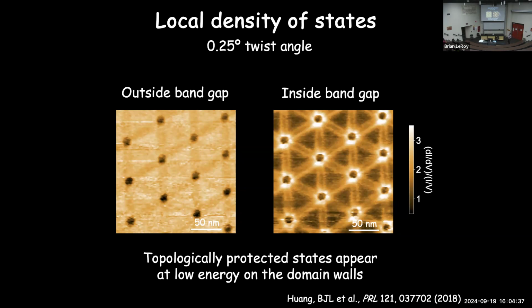As soon as you lower the energy, the AB and the BA sites, these triangles, their density of states goes down because you're within the band gap of them. But no matter how low you take that energy, there continue to be these two bright lines along the domain walls. And so these are topologically protected states. So the electrons live along these domain walls and still can transmit through the sample. If you were to do an electrical measurement here, this thing would still be conducting, even though you have all of these regions of insulating states in the center.